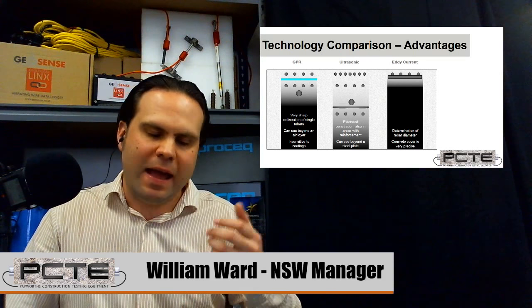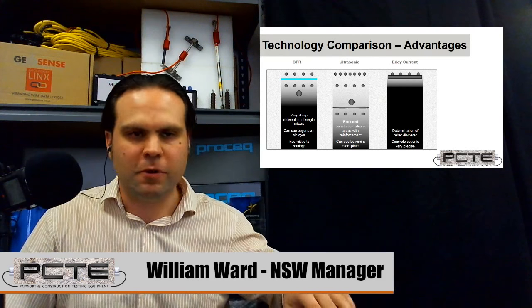Now, the advantages of the GPR is you're going to see the individual rebars very cleanly, and you don't need to bond the sensor onto the surface. So if you have a small air break, like a delaminating surface coating, if you've got to work over a rough surface and have to lay a plank, none of that's going to reduce your GPR's ability to be used. You might need to be a little bit more cautious in what you're doing, but the results are still available. Now, with ultrasonics, you can measure into complex areas, and it's also very sensitive to air.